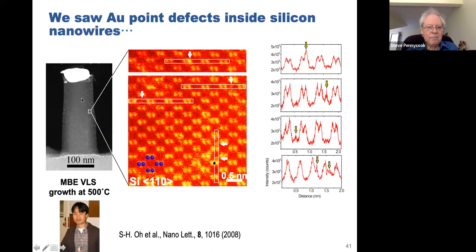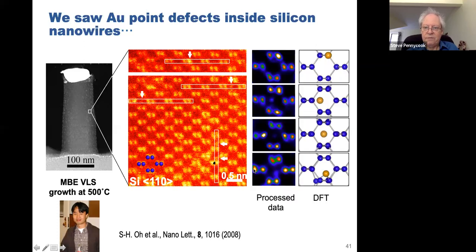He produced or found this nice nanowire sample. You can see it's got gold on the surface, but we could look inside. You could see the top surface and the bottom surface as you change defocus. So these are images from slices inside, and you can see substitutional gold here, interstitial gold here, here and here. And again, with some density functional theory, you could actually confirm that all these positions that we saw in the image were actually stable.